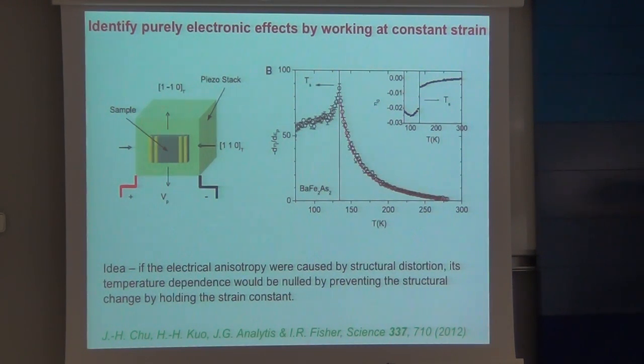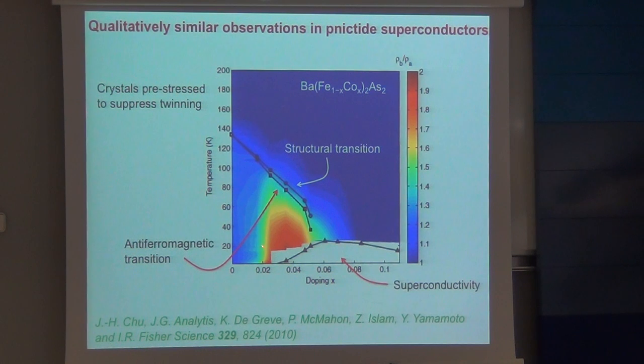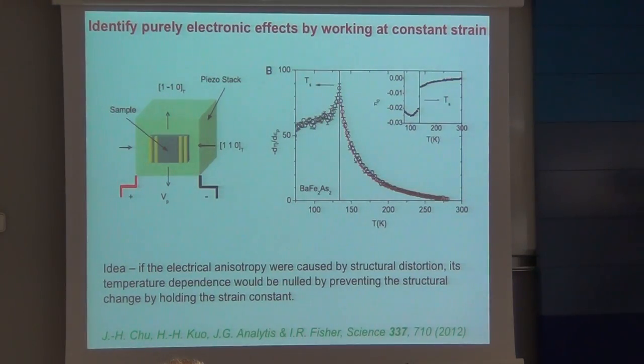So what they thought was that, okay, all the time here, they couldn't even observe this anisotropy unless they had pre-stressed the crystals, because the crystals have crystallographic twinning going on, and if they were strongly twinned, then you don't see the macroscopic anisotropy because you have domains of the anisotropy going in two directions. So, like in every other case we'll come on to, there's some sort of a symmetry breaking, macroscopic symmetry breaking field required in order to see the gross anisotropy. So here it was this stressing to suppress the twinning. So then the Fisher group said, okay, we're going to try and glue our samples to piezo-resistive stacks, and we're going to try and explicitly do the experiment under conditions of constant strain.